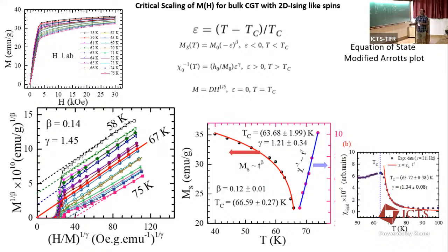And we also measured the actual susceptibility as a function of temperature experimentally. And of course, this also shows the same gamma, which is seen here. This is about 1.21, we got 1.31, but within the error bars, we found it to be the same. And there is another parameter, delta, which is related to these beta and gamma parameters, which you can figure out using this relation.